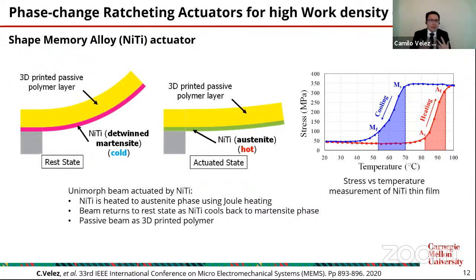It generates this hysteresis curve. And this is exactly what we are trying to extract from this material, this hysteresis curve, because it means that we can generate more stress in this sudden transition from martensite to austenite. I'm going to mark this transition with AS and AF, the start and finish of the austenite, and MS and MF, the start and finish of the martensite.